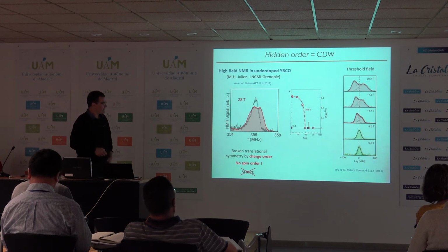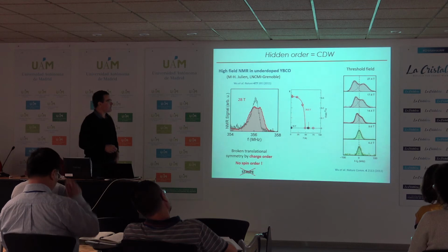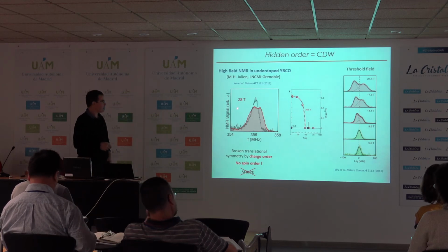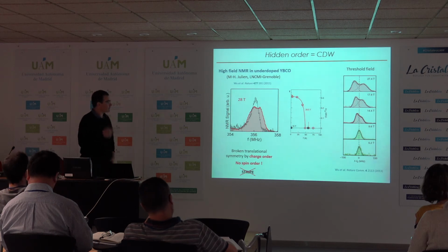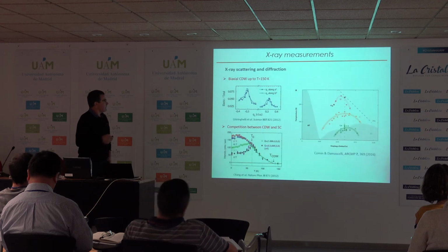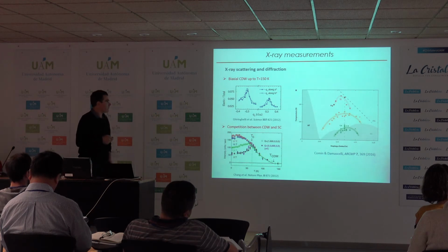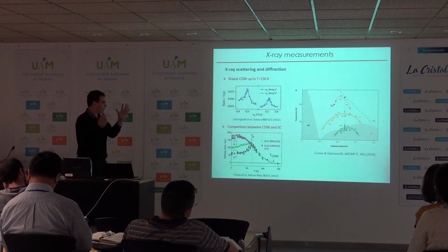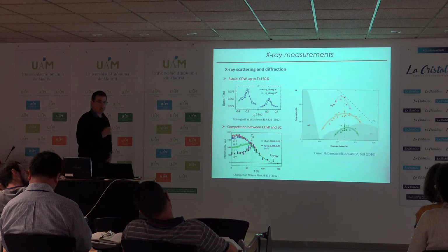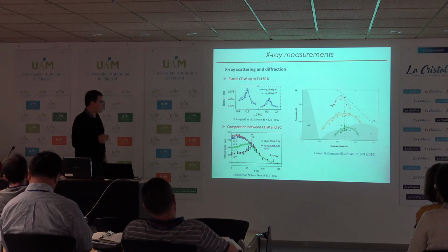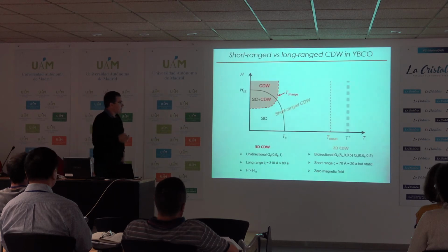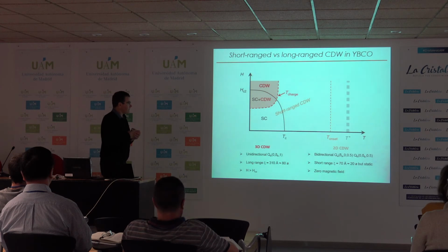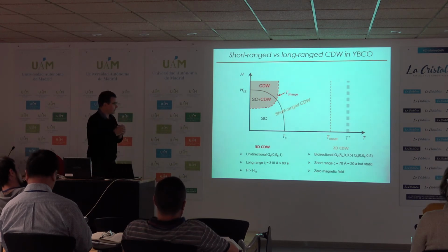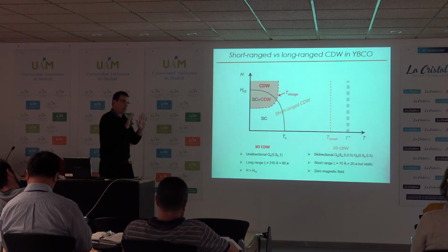And so this splitting, this charge density wave, appears above a threshold field. You need to be basically above 18 Tesla at this particular doping to start to see charge density wave. Of course, after this discovery by NMR, several X-ray groups have performed a tsunami of measurements. I'm not going to discuss that because Bernard will give a talk on that this afternoon. But the bottom line of all these measurements is that in YBCO, in fact, there are two types of charge density wave.